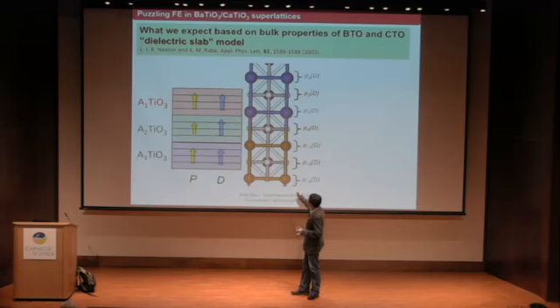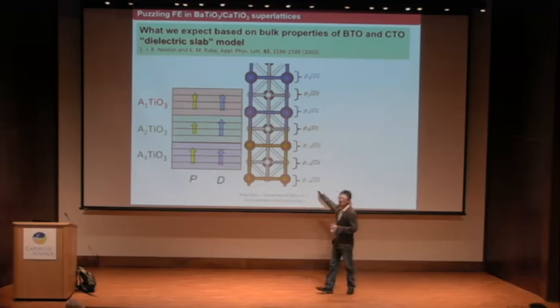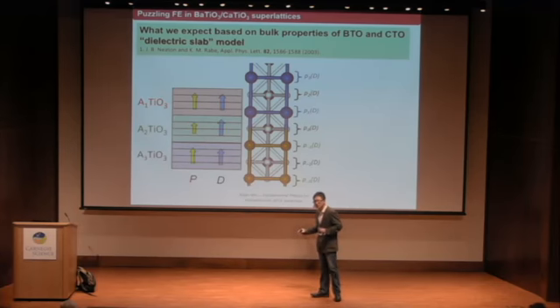Then you can build the superlattice by knowing the polarization. This polarization can be a local decomposition, or can be a unit-cell-based layer polarization as a function of D. Then you can build the dipoles based on the knowledge of bulk information, and eventually you can get everything out for the superlattice. The bulk can be many bulks.